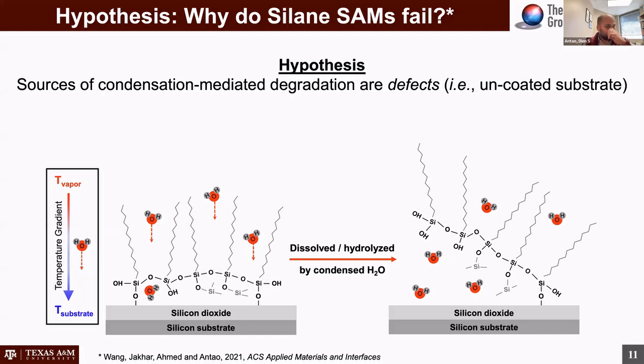And the idea here is that the process of condensation is different from even doing a contact angle measurement where you have a sessile droplet on the surface. The act of condensation actually creates this potential that drives vapor to the surface. And of course, vapor will be attracted to the locations of high surface energy, which would be these regions that are uncoated on the substrate, because typical metal oxide surfaces are high surface energy materials. So we did two simple experiments.